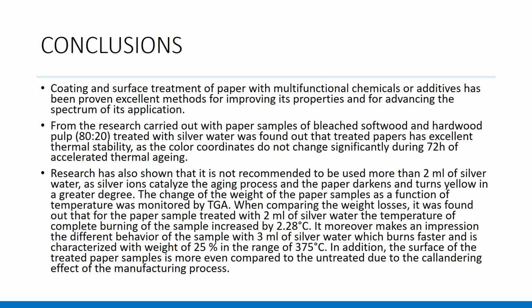375 degrees Celsius. In addition, the surface of the treated paper samples is more even compared to the untreated due to the glazing effect of the manufacturing process.